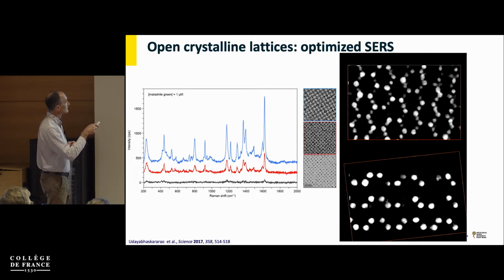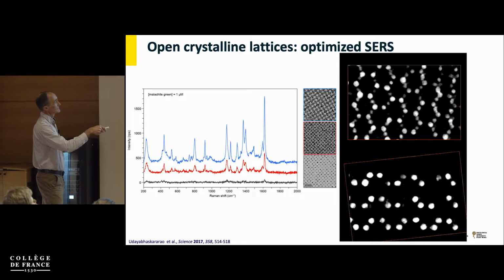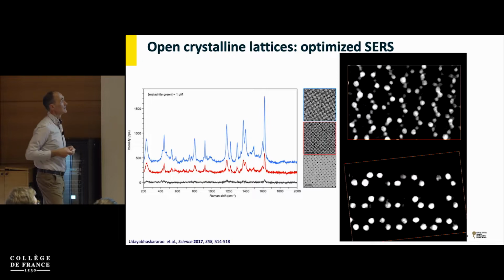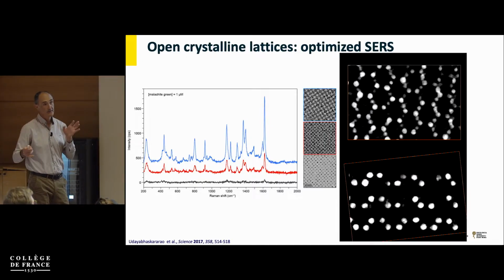So if you think about surface-enhanced Raman, this would actually be very nice because the analyte molecules could diffuse through the big pores and then deposit at the gaps between the nanoparticles everywhere. And the films are thin enough that you will obtain a signal from every layer in these multi-layers. And so this is what you see for different assemblies with more and more layers. For the monolayer, there is nothing because the particles are too small and too far from each other.